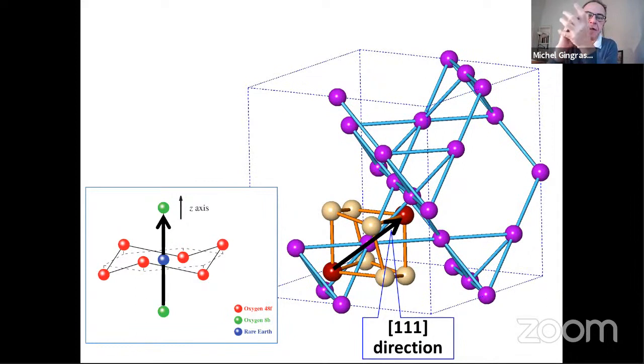To give you an idea, the distance from the rare earth to the red oxygen centered in the middle of the tetrahedra is about 2.2 angstrom, while the distance from the rare earth to the six oxygens that are in the equatorial plane is about 2.5 angstrom. So it's a highly distorted environment, and that distorted environment is responsible for the anisotropy acting at the site of the rare earth. Depending on which rare earth, which lanthanide, is occupying the lattice, you can have different forms of anisotropy, either an Ising anisotropy or an XY anisotropy.